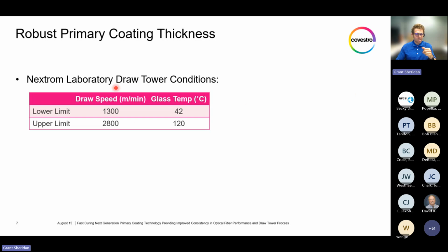Shown here are our process limits. We varied the draw speed from 1300 to 2800 meters per minute, as well as had varying glass temperatures from 42 to 120 degrees Celsius.